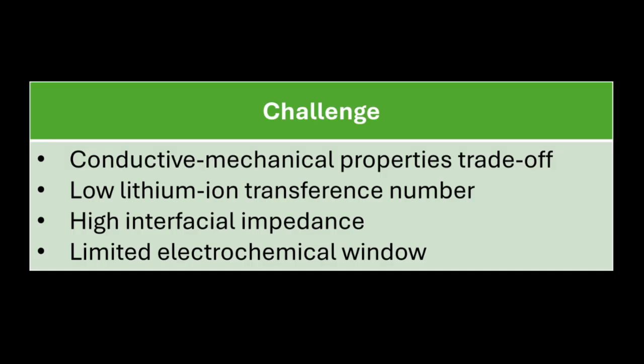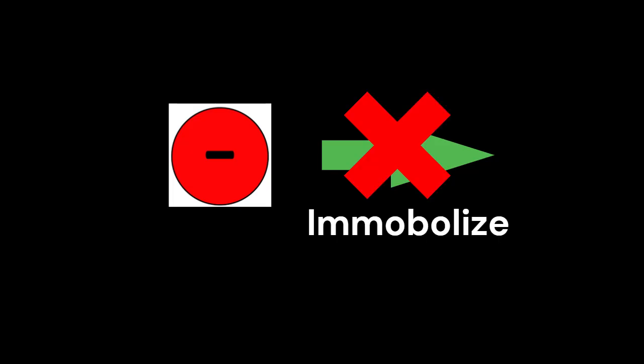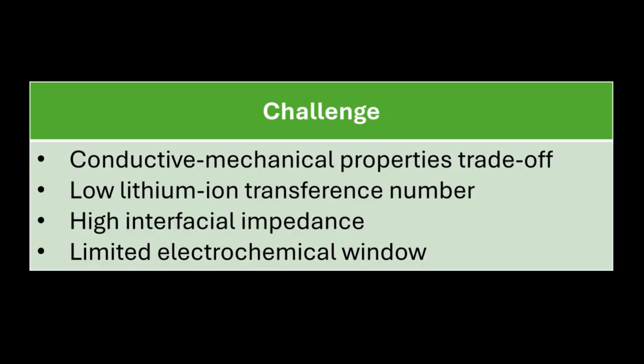Another challenge is the low lithium-ion transference number, which leads to dominant anion transport and uneven lithium deposition. One important research direction is therefore to immobilize anions on the polymer chains. In addition, high interfacial impedance between the electrodes and electrolytes, as well as a limited electrochemical oxidation window for high-voltage cathodes, remain important issues to address.